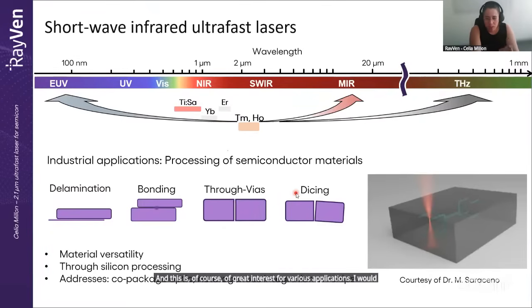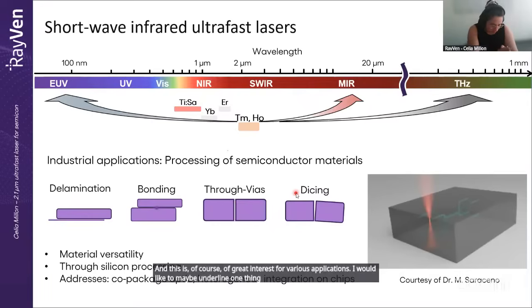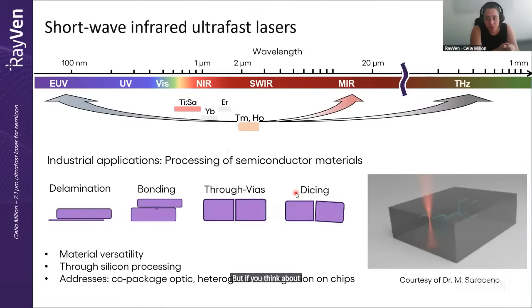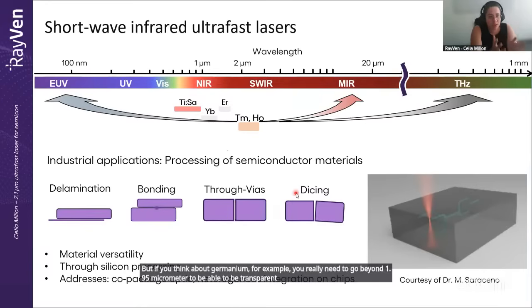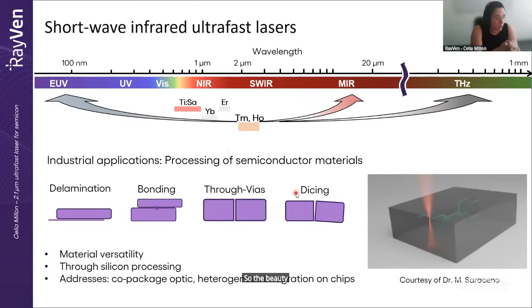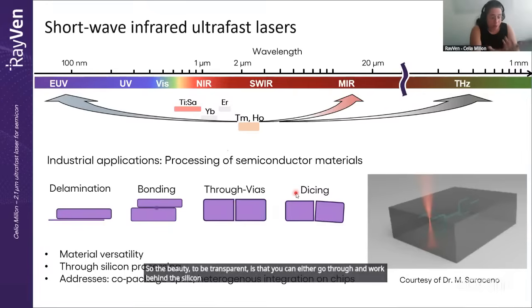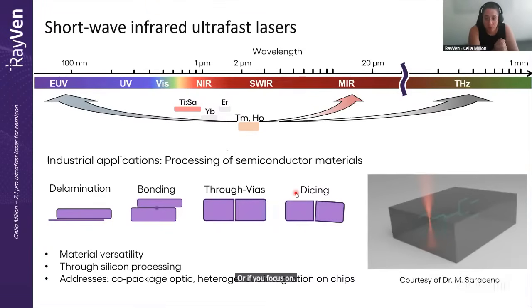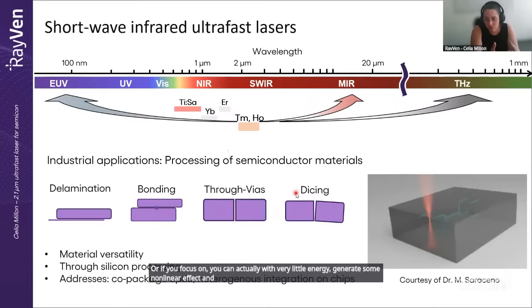I would like to maybe underline one thing. The silicon starts to be transparent at 1.5. But if you think about germanium, for example, you really need to go beyond 1.95 micrometer to be transparent. So here you see that there is an interest in being above 2 micron. The beauty of being transparent is that you can either go through and work behind the silicon, or if you focus down, you can actually with very little energy generate some nonlinear effects and inscribe directly in the bulk of the silicon without damaging the surface.